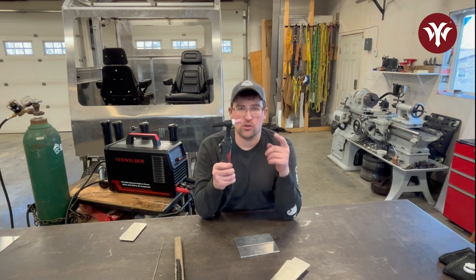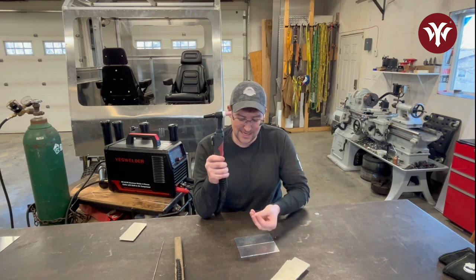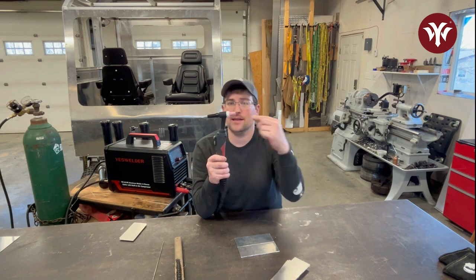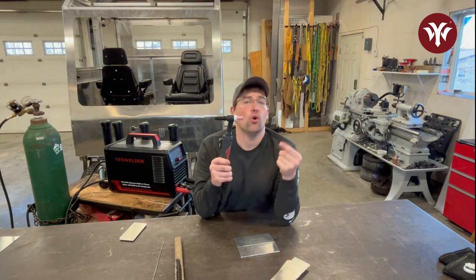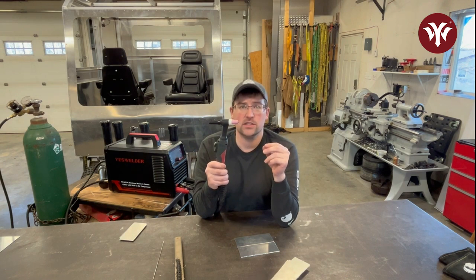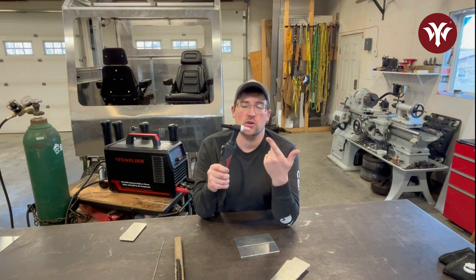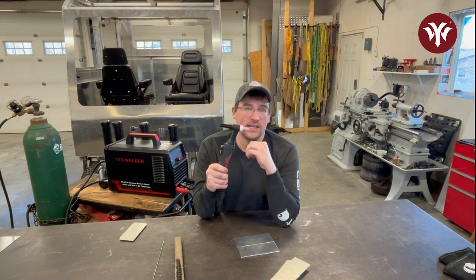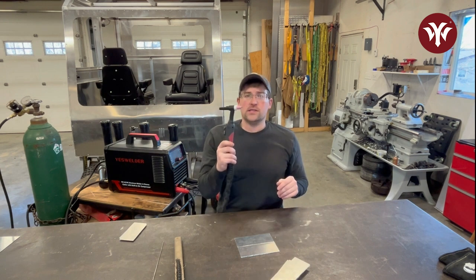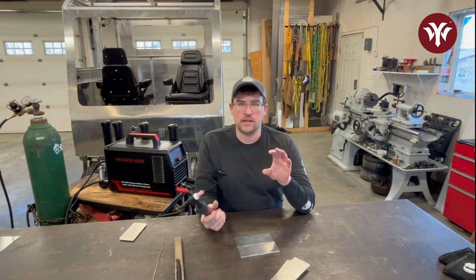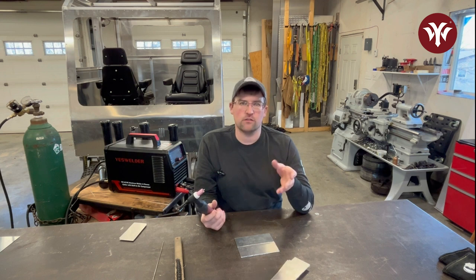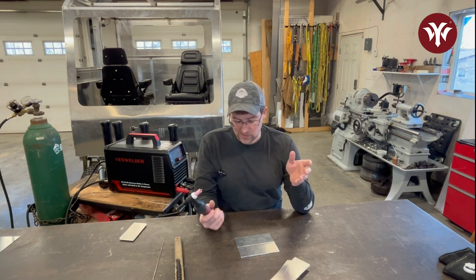The other issue is if you crank the balance too high, as I said, the electrons are coming out of the part into the tungsten. What that's going to do is overheat your tungsten. Tungsten is really good at operating at high temperatures, which is why we're using it as an electrode, but it can only handle so much current and so much heat before it just melts out. So it's always best to try and find the balance that's going to work best for you. And it's really trial and error.